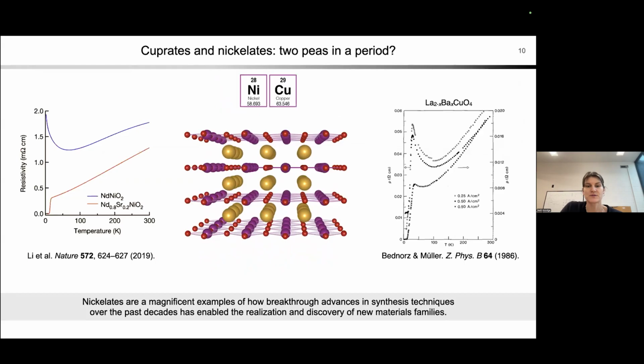So here's the atomic structure you see here. We've just tipped those planes down, and those are now nickel oxide planes instead of copper oxide planes. And you see the comparison of the resistivity over here on the left. So very exciting: nickelate superconductivity finally demonstrated, but not until 2019. Again, there's 2 decades between the prediction and the stabilization of these materials.